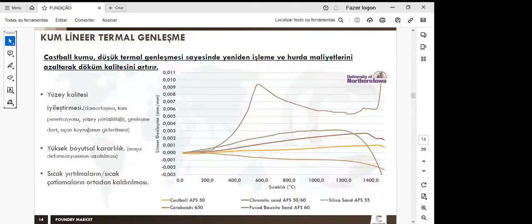Now we're talking about thermal properties. In this slide, we can see a graph that shows Castball thermal expansion behavior in comparison with silica, chromite, mullite, and a fused bauxite sand. Silica sand presents the highest thermal expansion, as we know. Chromite and fused bauxite sand have low thermal expansion, but above Castball and mullite sands. The low thermal expansion of Castball provides the casting with excellent surface finish, high dimensional stability, and elimination of hot tear defects.